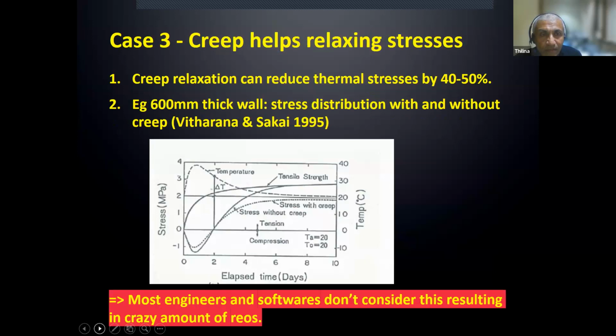Case 3, creep helps relax stresses. As I said, anybody not using the benefit of creep relaxation can come up with crazy designs when it comes to reinforcement. In this case, the 600 millimeter wall stress distribution, the tensile, you can see the same temperature development. The calculated stresses are much higher in the bold line compared with the dotted lines. So that's one reason. Probably when you take some structural programs and put in these temperature gradients and calculate stresses, you get very crazy numbers, and then you start putting in reinforcement as well. Some reinforcement is so heavy, and I wonder why, when we had uncracked concrete 30, 40 years ago without any reinforcement sometimes. Okay, next one, please.